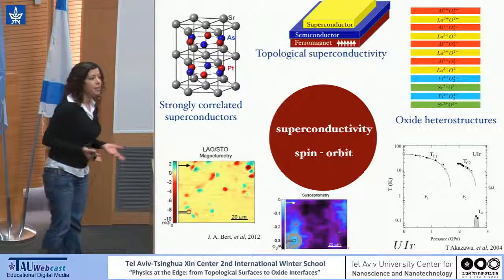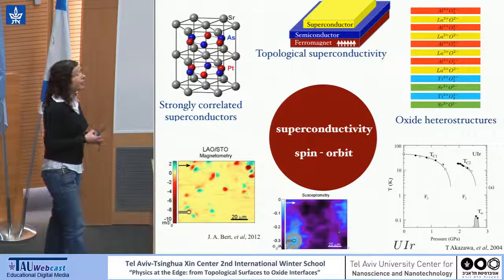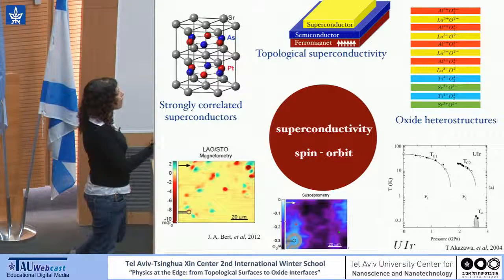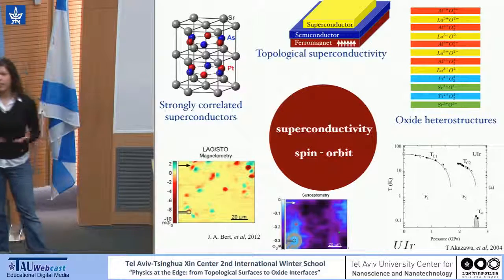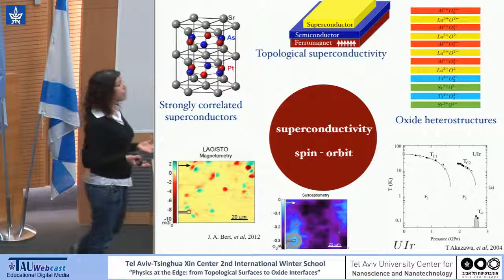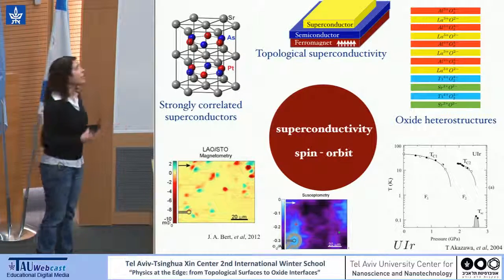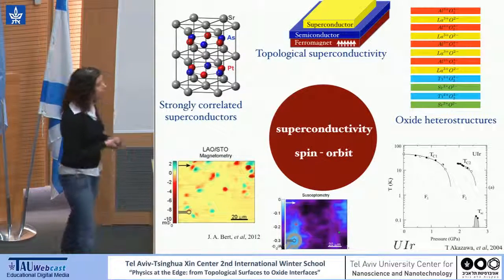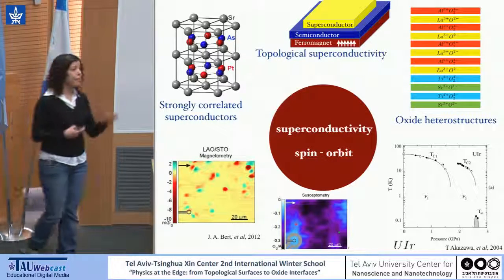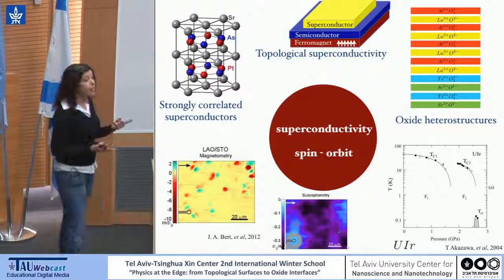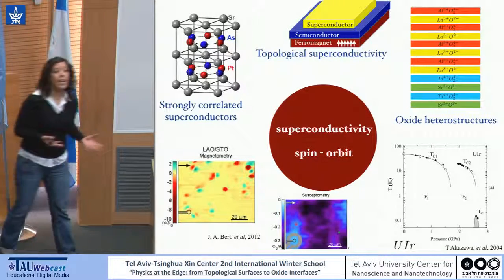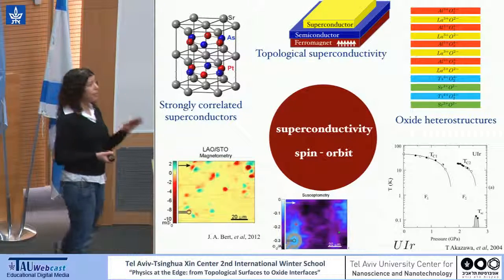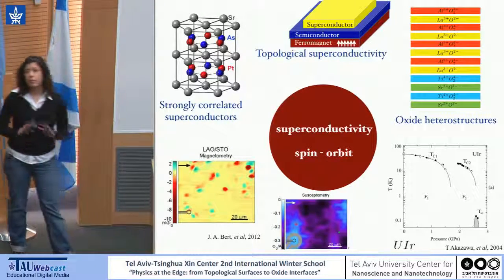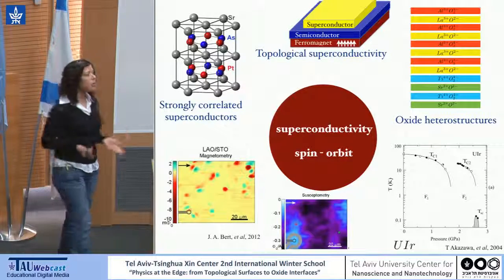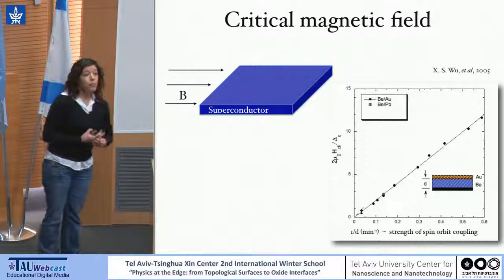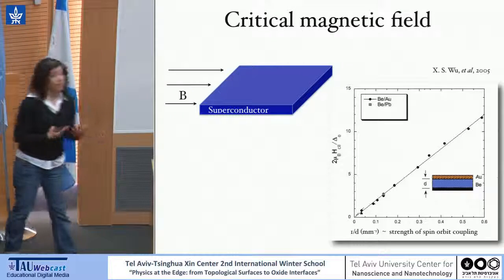Or, as we had in the previous talk, where superconductivity is present in the background of some magnetic order. It seems to be that this magnetic order is actually very inhomogeneous. However, there is magnetic order in the system, and we have superconductivity and spin-orbit coupling. So now the question is what this interplay between 3 things, superconductivity, spin-orbit coupling, and ferromagnetism can do to the phase diagram of such system. So let me start by thinking about not fluctuating magnetism, but just constant magnetic field, external or internal in the system.